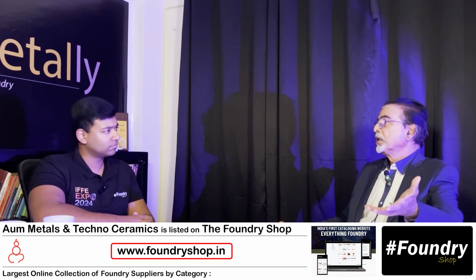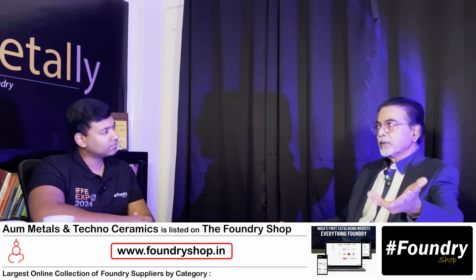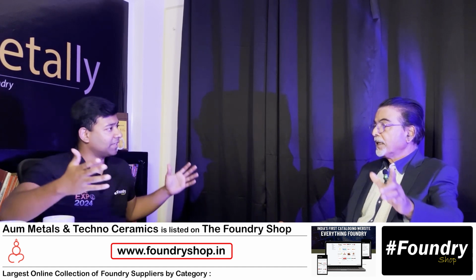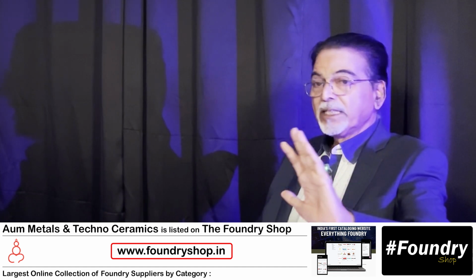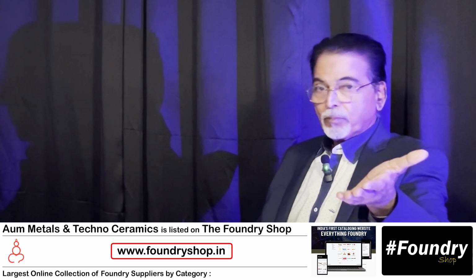It can also be used for non-ferrous, but today we are more into ferrous casting. What about cast iron? When cast iron castings are very huge, say more than 1 ton, riser removal again becomes difficult. So mainly bigger castings. And because of very high carbon and silicon, it doesn't gas cut easily. Many of those foundry people who are making cast iron are aware of this fact. So with this breaker core, you can hammer the riser and remove it. So those are your use cases for breaker cores.